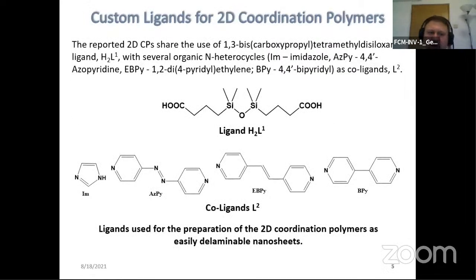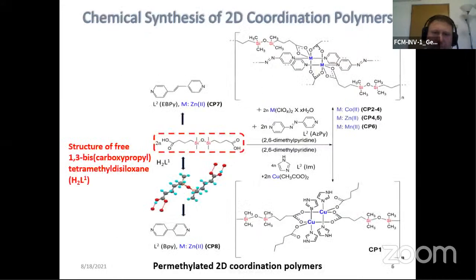So, for preparing two-dimensional coordination polymers as easily delaminable nanosheets, we used 1,3-bis carboxypropyl tetramethyl disiloxane ligand, marked here as H2L1, and several organic nitrogen heterocycles as core ligands. Now, the permethylated coordination polymers were synthesized by using coordination chemistry, mainly a dicarboxylic acid with the tetramethyl disiloxane spacer as anionic crosslinker, marked here as H2L1, in combination with nitrogen heterocyclic compound as neutral ligand, marked L2, for multiple transition metals from metal salts, marked MX.